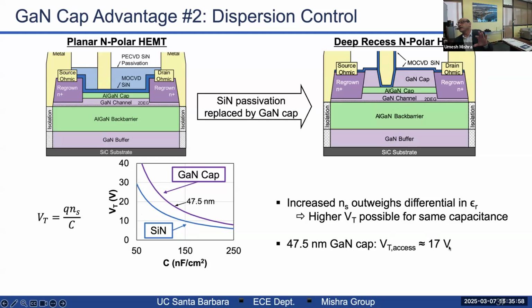We typically design around 20 volts. And this is around 6 volts. So between 6 and 20 volts, the surface doesn't even play a role. And after that, the silicon nitride passivation kicks in and helps the dispersion to remain low. So we have a 2-level dispersion control. One is at the epitaxial layer, which is the GaN, and a silicon nitride on top.